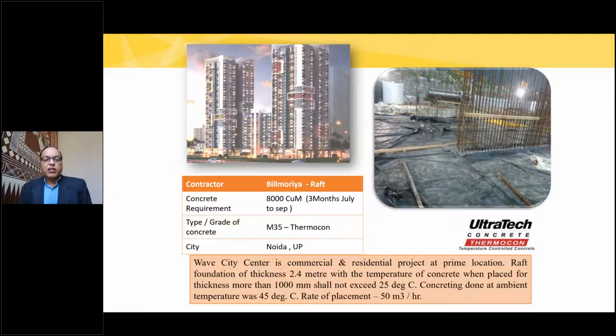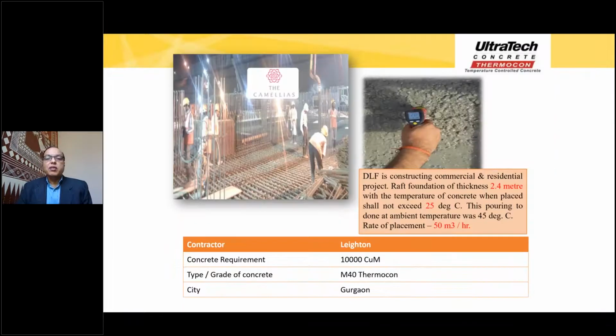Because the thickness of the raft foundation was 2.4 meters. You can imagine a 2.4 meters thick concrete foundation. Therefore, the temperature of concrete, when you place it for a thickness of more than 1 meter, should not exceed 25 degrees centigrade. That was the condition, and the concreting was done at ambient temperature, and the rate of placement was 50 meter cubes per hour.